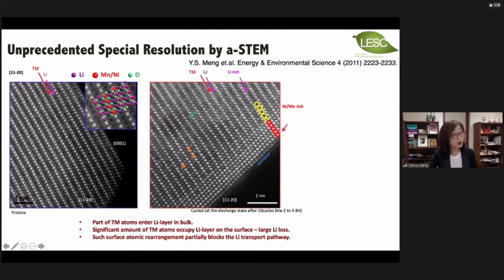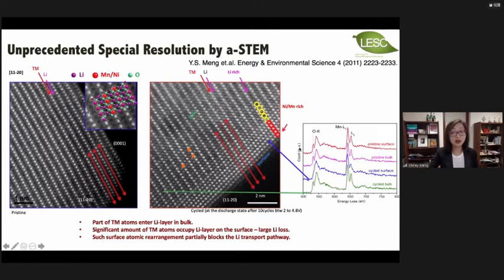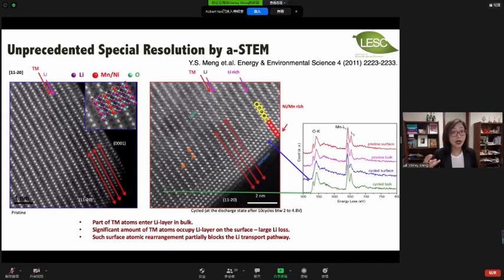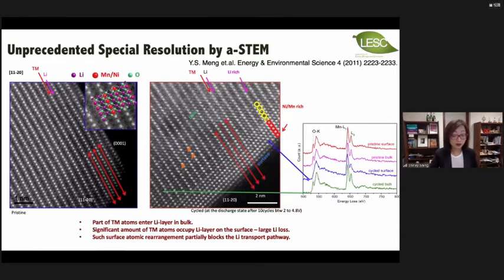And the change is very subtle. After high voltage exposure, you actually see the lithium and transition metals swapping their positions, but the major phase change is only on the surface 2 nanometers, right? And this phenomenon can be easily missed in the traditional diffraction-based techniques, but with this kind of new fancy tools, we can then detect the structural and chemical change on the high voltage cathode materials. And since then, the entire battery field always knows the cathode particle surface has to be protected with some kind of very robust coating so that the battery can operate a long time at high voltage.